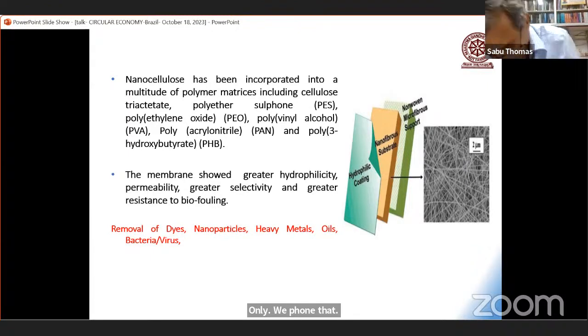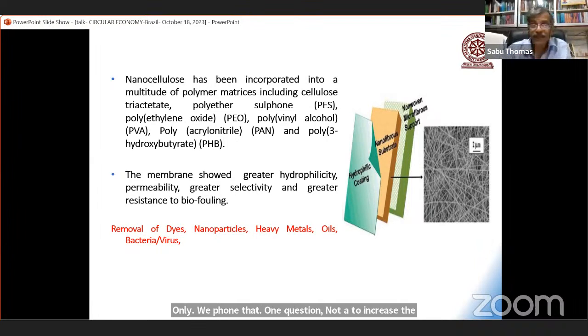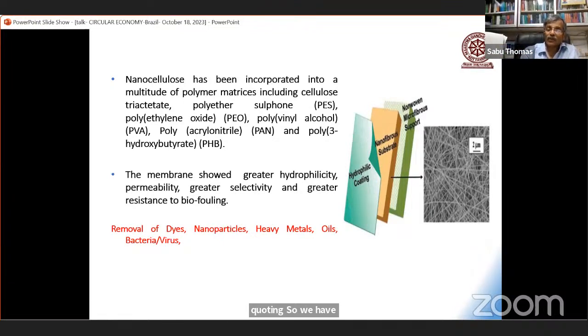In order to increase the efficiency of the commercial filter, we decided to give a coating of nanocellulose. So we have given a coating of nanocellulose at the surface of the filter. Yes, students, once you give the coating, the advantage is the hole size becomes very small because you have nanocellulose. The system becomes more hydrophilic, so water can diffuse very easily.